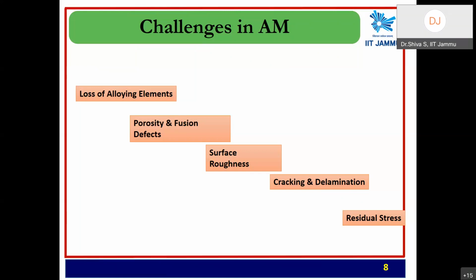It is followed by porosity and fusion, because there might be certain elements which are highly sensitive to oxidation in the surface atmosphere, and these oxide gases get entrapped within the solid structures, eventually leading to space and voids, which might pull down the quality of the product. And once the alloying and the porosity are attained as per the requirement, the next challenge will be the surface roughness, as I said. Because when there is too much surface roughness, the crack propagation point starts at that particular level itself.